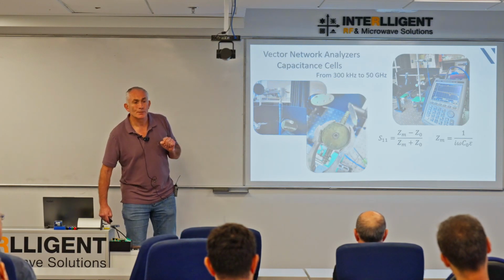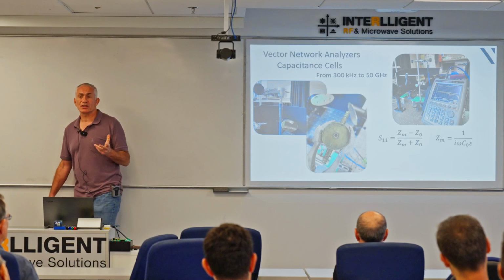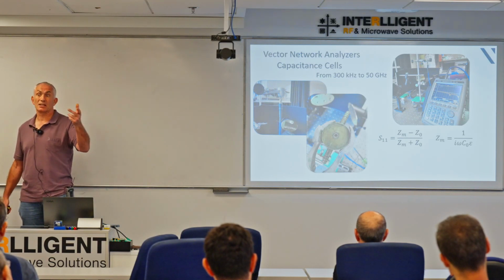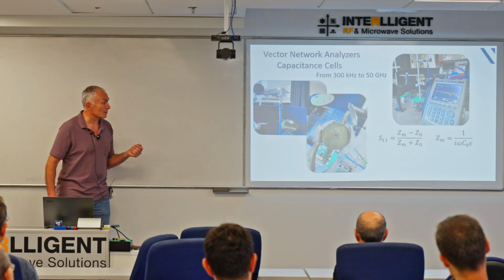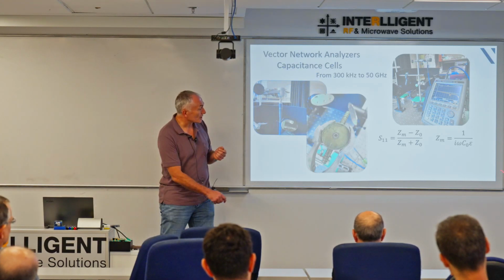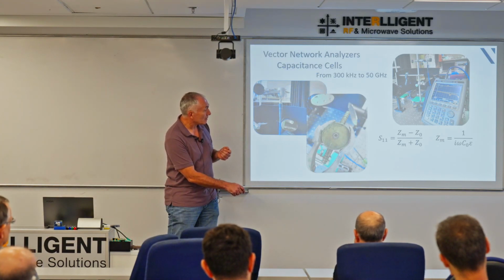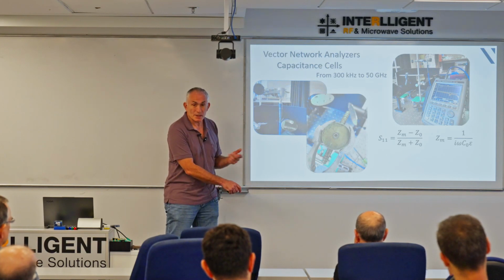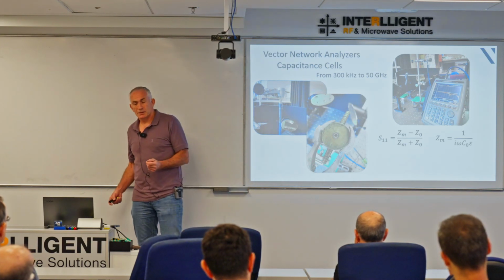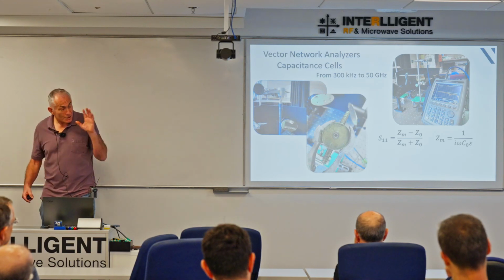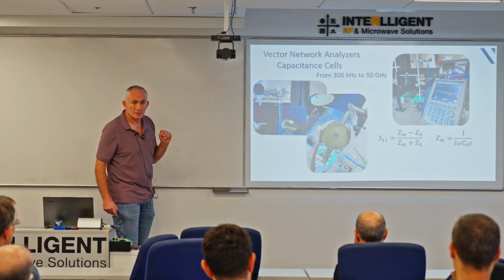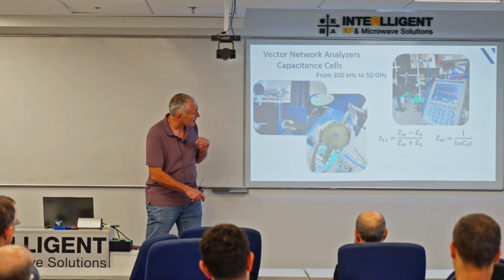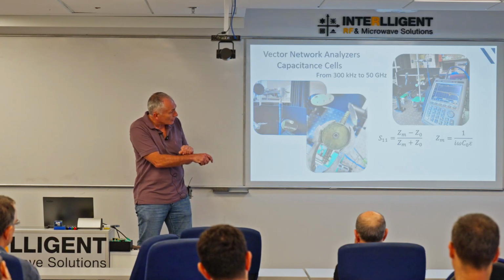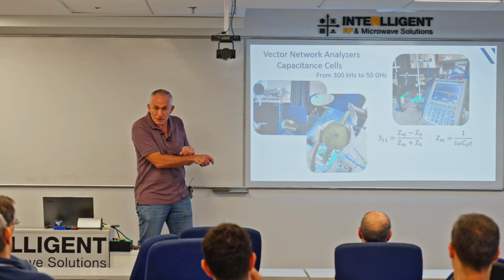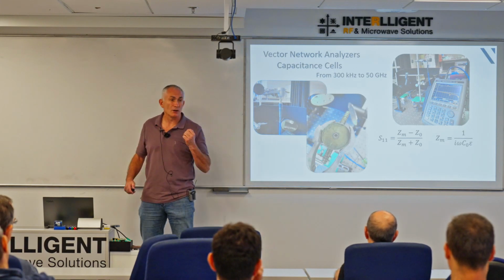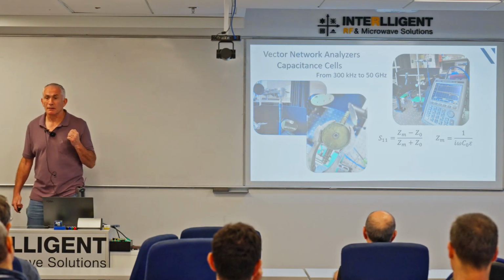Simple relationship between S11 and the impedances at the end of that line. So we're looking basically at an impedance mismatch. And we're measuring from the impedance mismatch. Okay, now once again, the impedance of our sample is quite simply the impedance of a capacitor. So it's very simple. There are limitations on how far you can go with that. You are going to get multiple reflections inside this cell, and you can actually see here on the screen that we have multiple reflections starting as we creeped up beyond about 5 gig, I think there.